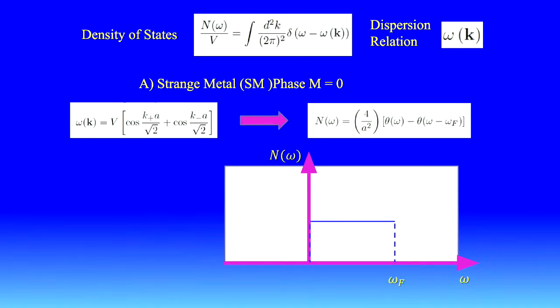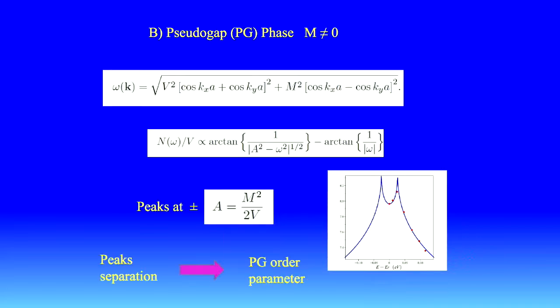So that's the definition of density of states, where ω(k) is the dispersion relation. If we use the result of the energy for a tight binding system, we have just this. Now, if we add the pseudo gap, we obtain this function, which has this form here. You see the two peaks, and the line is our theoretical expression, and the dots are the experimental values.